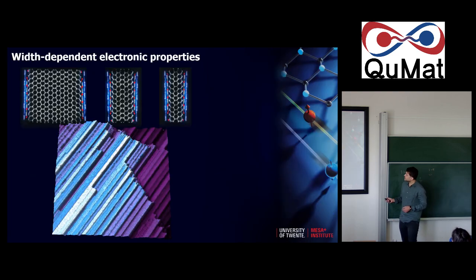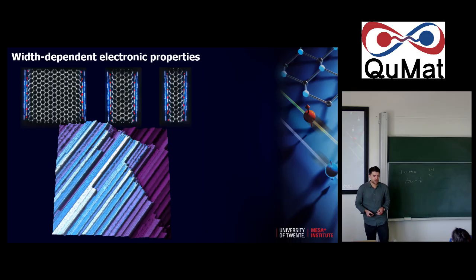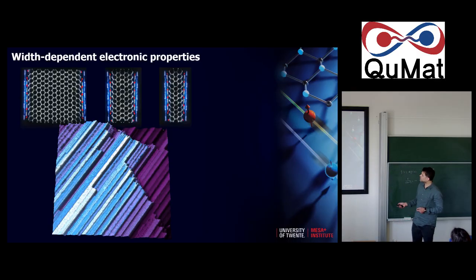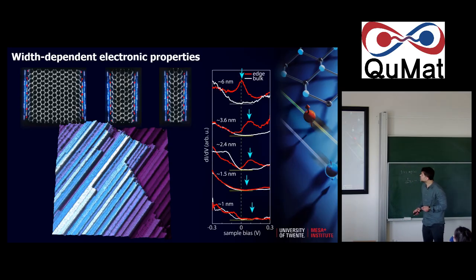Okay, so the first thing that we want to look at is what is happening as we reduce the width of the nanoribbon. So we look at nanoribbons. You can see another example here of many nanoribbons, and you see that some of them are a little bit wider than the other ones. So we want to look at the width dependent electronic properties, and this is an example of that. It's a very wide nanoribbon here. You again have these metallic states at the edge. And as you make the ribbon smaller, and narrower, then at 3.6 nanometers, you still have an edge state.